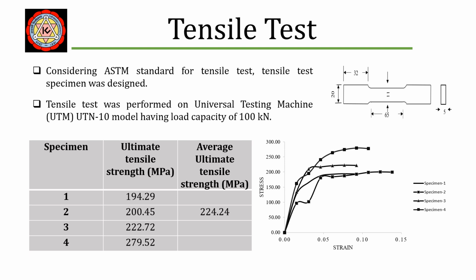This is the stress-strain curve of all four specimens. The result obtained for the ultimate tensile strength might not be accurate, but this stress-strain curve shows the trend of the failure. No necking was observed during the test of all four specimens.